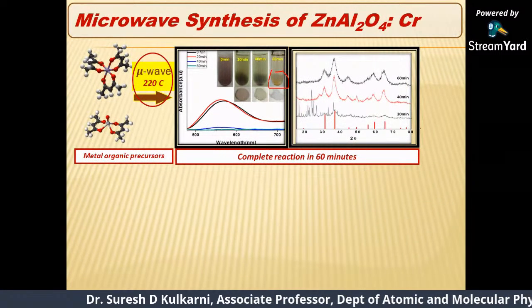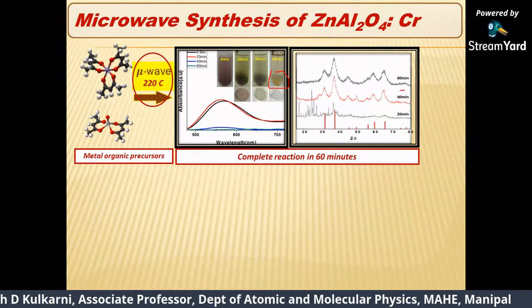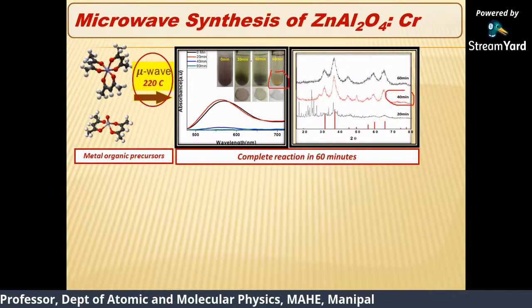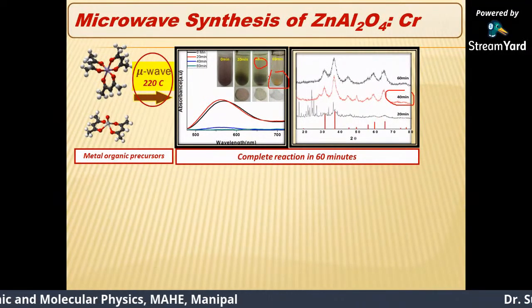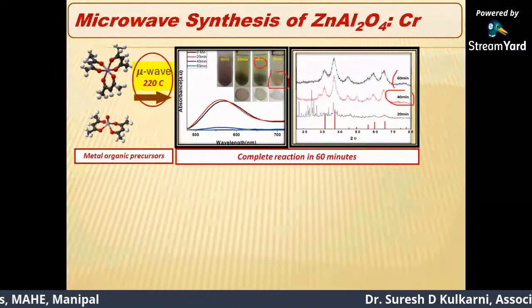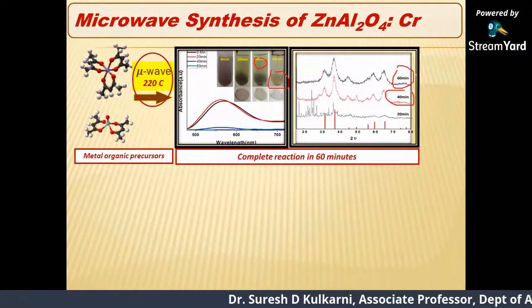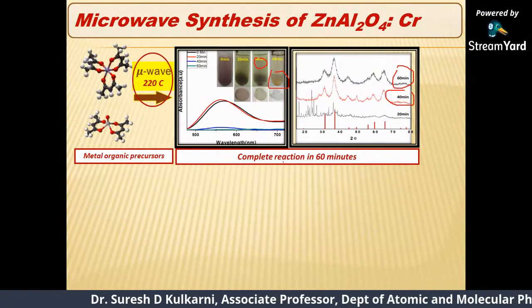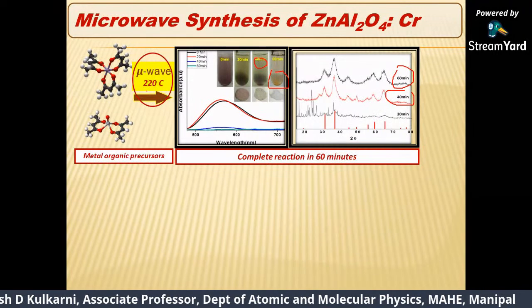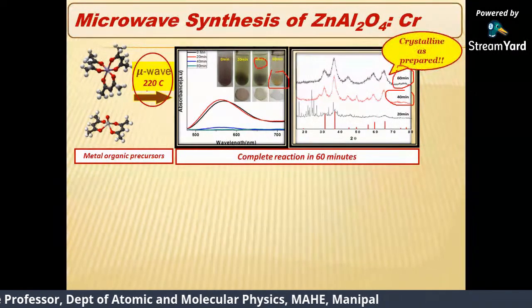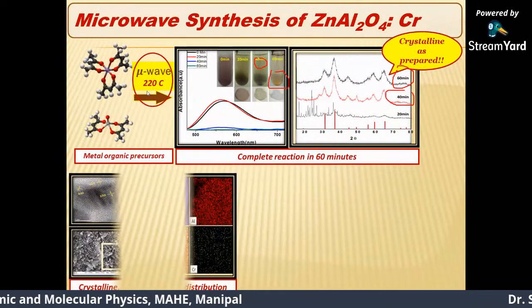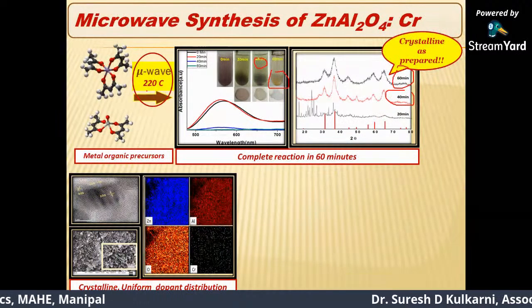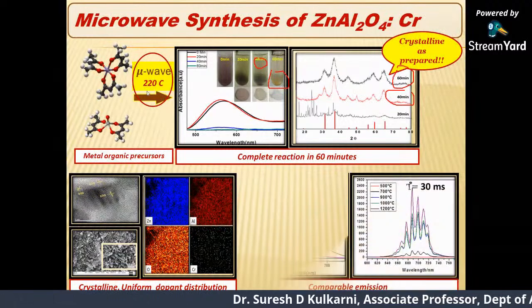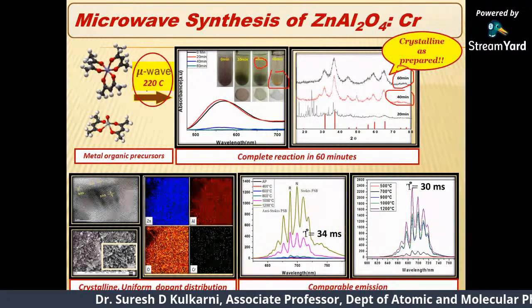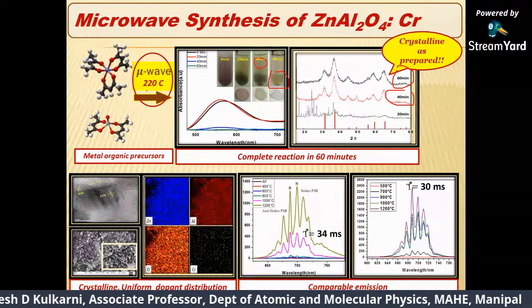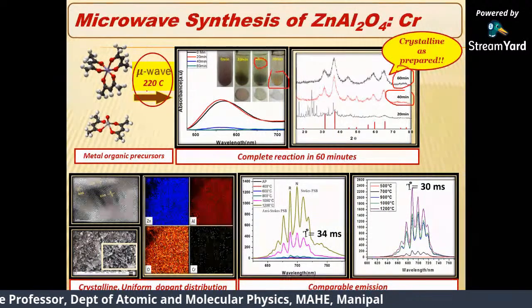When we started doing the synthesis, you can see that at 40 minutes we have the material formed, but the green color tells me all the chromium has not gone, and therefore we optimize the synthesis time to about 60 minutes. At 60 minutes and 220 degrees I am able to prepare this material, which is crystalline in the as prepared form. Again, various characterizations show that particles are quite small, dopant distribution is uniform, chromium is distributed everywhere uniformly, and look at the very nice emission pattern.